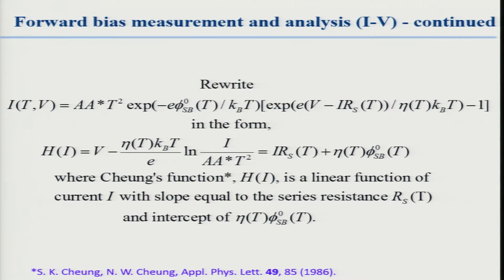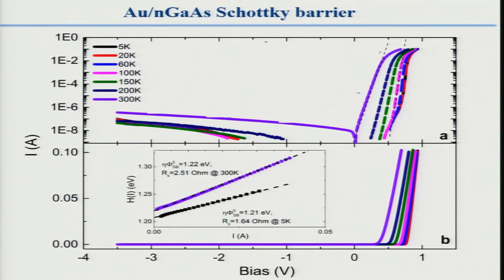We rewrite the current voltage characteristic. And this was done by Cheung. It's called Cheung Analysis. You rewrite this. Essentially, this form is this equation, the thermionic emission current, rewritten. It's called Cheung's function. It's a linear function of current with a slope equal to the series resistance. So we have a way of measuring the series resistance and the intercept. And the intercept is a product of the ideality and the 0 voltage Schottky barrier height. This Schottky barrier height, remember, is an extrapolation to 0 voltage. That's why we call it the 0 voltage Schottky barrier height. It's not the real Schottky barrier, which would be under what we call flat band conditions. So let me explain that again.